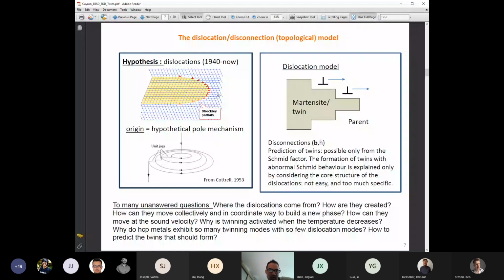So in this theory, that is called disconnection, sometimes you need very specific kinds of dislocation to readjust the position of the atoms. So in this disconnection model, they assume that the martensite or the twins, the reorientation, is the result of movements of specific dislocations. So I try to represent this situation on the right part, where you see dislocations. Here it's edge dislocations that go from the left to the right. And if they are stacked in a specific order, and if their Burgers vector is also specific, you can, with this model, transform an FCC, for example, into BCC, or FCC into HCP, with partial Shockley dislocations, for example.